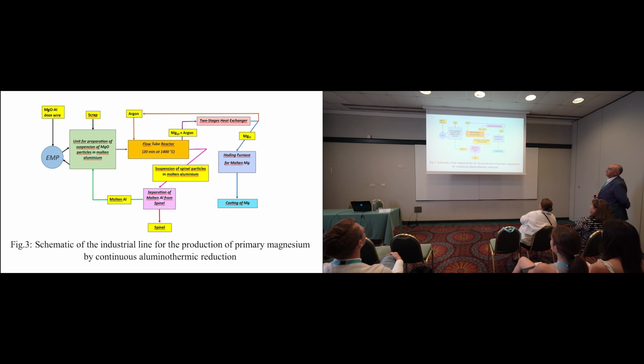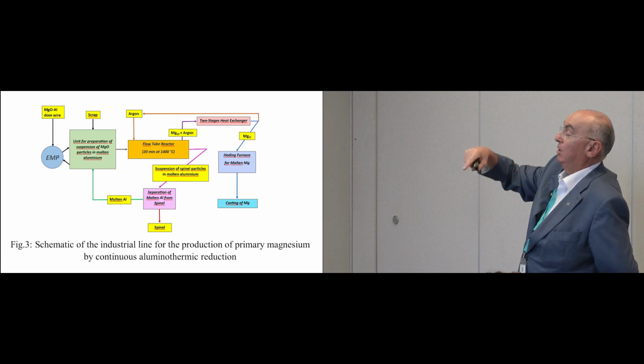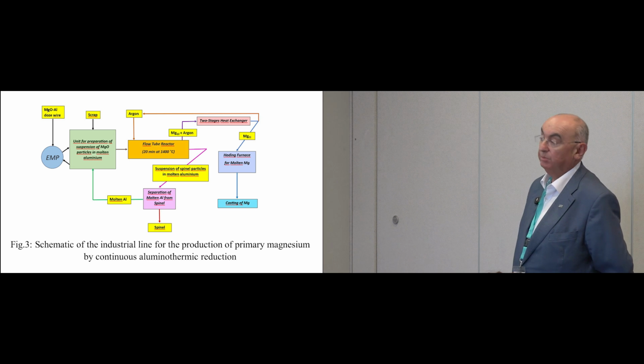We said 20 minutes at 1,400 degrees. Under this condition, magnesium is gaseous, and with argon, you put magnesium gas into a 2 stage heat exchanger, which is a convenient unit. Also, if you are producing magnesium by electrolysis or by Pidgeon process, you should get this heat exchanger. And then of course, liquid magnesium in holding furnace, and then you can cast magnesium ingots.